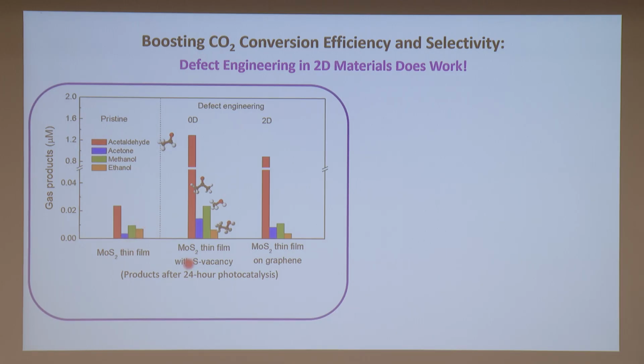However, if you do sulfur vacancy modification by the hydrogen plasma, then all of a sudden you have at least 2 orders of magnitude increase in one of the products. In this case, it is acetaldehyde. Acetaldehyde just shoots up, while the other products still remain quite low. And if you do the heterostructure with MoS2 on top of graphene, you also see very effective boosting of selective product. So this does work in the thin film case.